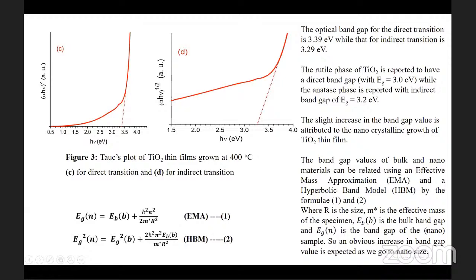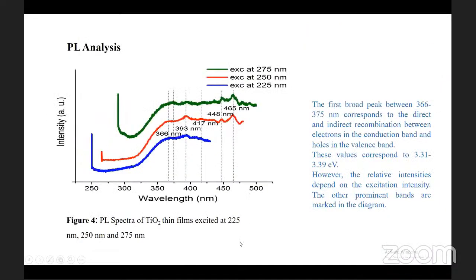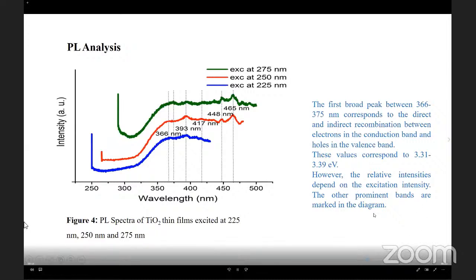Band gap values of bulk and nanomaterials can be related using the effective mass approximation and hyperbolic model by formulae 1 and 2 given here. PL analysis, photoluminescence analysis. The first broad peak between 366 and 375 nanometers corresponds to the direct and indirect recombination between electrons in the conduction band and holes in the valence band. These values correspond to 3.31 and 3.39 electron volts. However, the relative intensities depend on the excitation intensity. The other prominent bands are marked in the diagram.